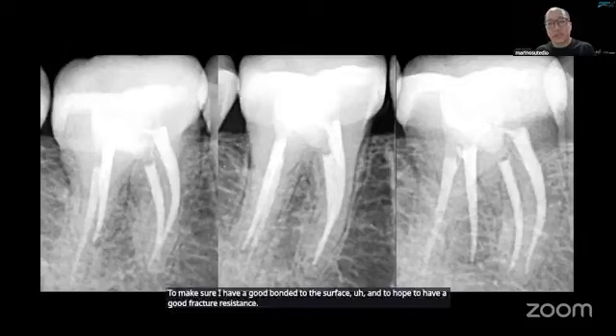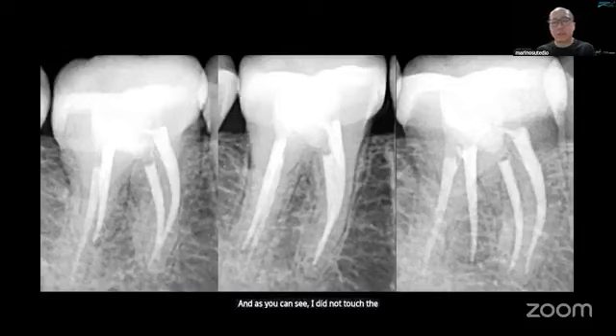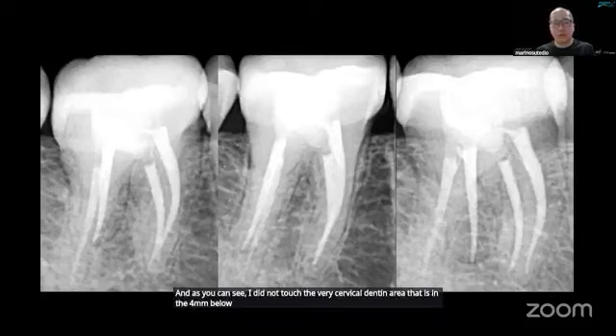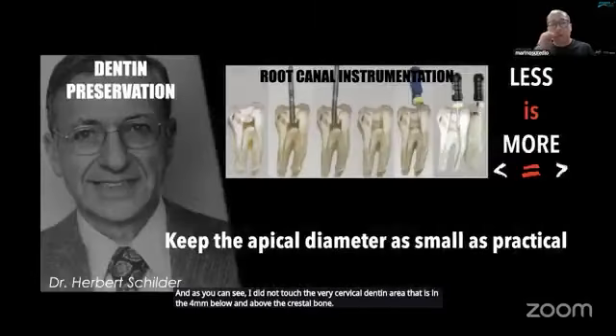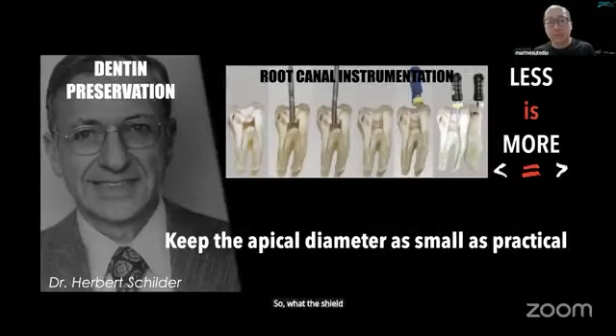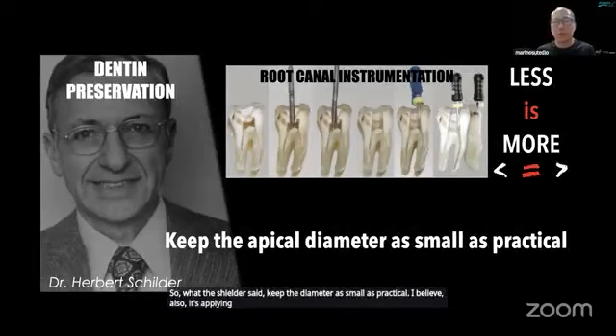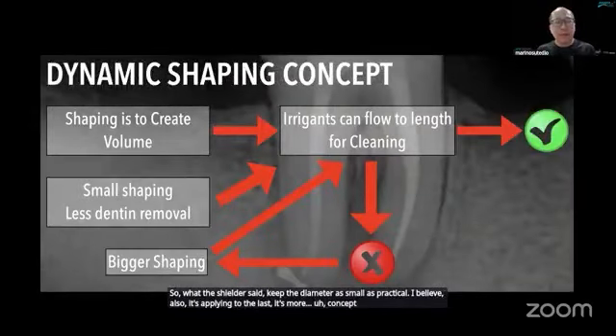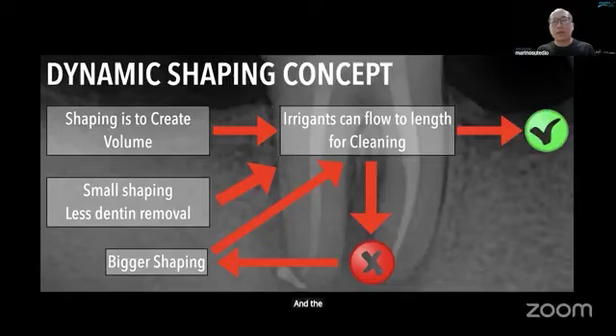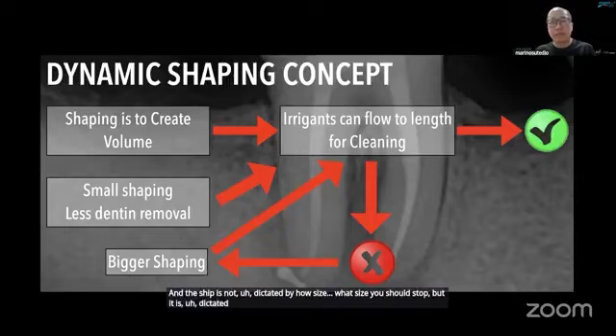And as you can see, I did not touch the pericervical dentin area, that is the 4 millimeters below and above the crestal bone. So what Schilder said, keep the diameter as small as practical. I believe it also applies to the less is more concept. It means you need to create a volume by shaping, and the shape is not dictated by what size you should stop at, but it is dictated by the anatomical evidence.